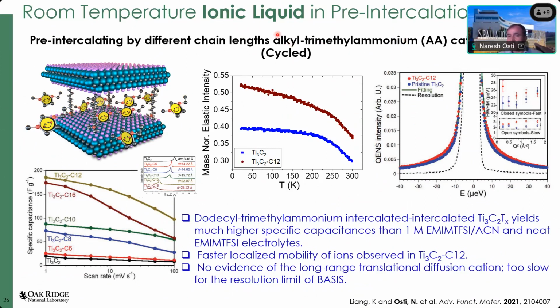We tried alkyl groups of different chain lengths, from C6 all the way to C16, which shows a gradual increase in the d-spacing. But if you look at the capacitance, we found the maximum capacitance with the cation with the C12 carbon chain. It means that this is the optimum cation that increases ion transfer in between the layers. A longer chain hinders the mobility of the ions between the layers. That's why you end up getting lower capacitance with the 16 carbon chain.